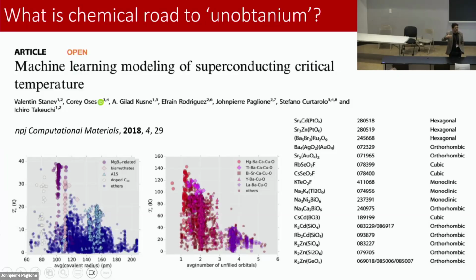But the temperature is really determined by how much you want to dissolve your reagent. In our case, for the iron-based superconductors, we wanted a low temperature because we wanted to slowly dissolve iron metal in there. If you dissolve it too fast, or say I started with iron 2 chloride, something like that, I make a whole bunch of iron oxides, which are ferromagnetic impurities, right? And then you don't get to see your superconducting phase. And so it depends on the species that you're starting with and how fast you want to dissolve it, I would say. You definitely have an upper limit, as I said, 220 degrees Celsius, because your Teflon decomposes.